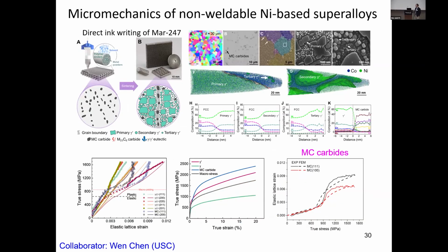Recently, we also studied another kind of heterogeneous microstructure using APS synchrotron diffraction. In this case, we print this non-weldable nickel-based alloy using a different method. It's called direct ink writing. This enables us to print the non-weldable superalloys. And those alloys certainly produce the well-known gamma prime microstructure. In addition, they also produce nanoscale carbides.